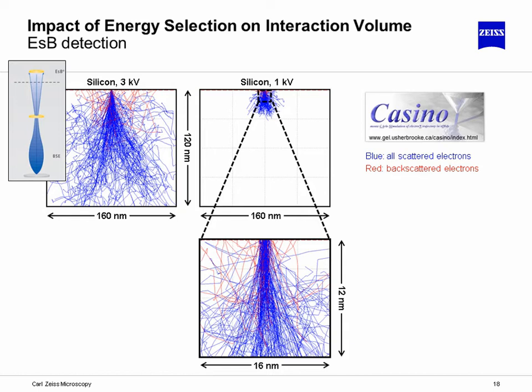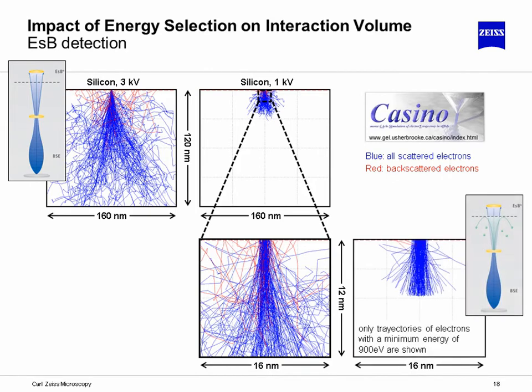If we now focus on the red trajectories of the backscattered electrons, you see at 1 kilovolt, using a so-called energy selective backscatter detector, it is possible to select a window of energies to only detect so-called low loss electrons. That is, backscattered electrons that have lost only a small amount of their original energy. These come from very near surface regions. In the last plot of the slide, only trajectories of electrons that have lost a maximum of 100 electron volts of energy are shown.